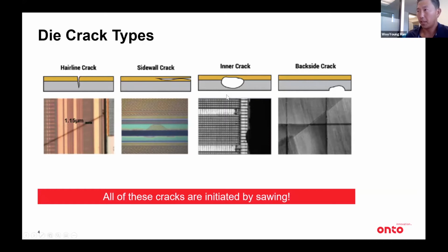And the third type here is the inner crack, and this is the most difficult crack to detect because on the surface it looks good. It's actually chippings or cracks going below the wafer surface or die surface. So it's very difficult to detect. And the fourth one is a backside crack. This is a crack that happens on the backside of the wafer, but doesn't really continue up to the top surface of the wafer.